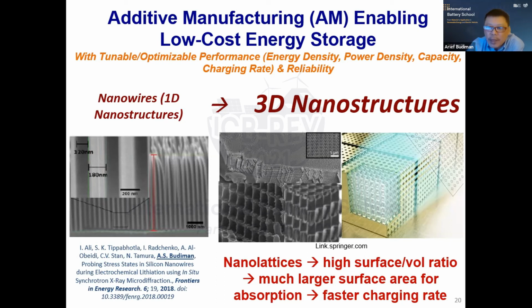Now that we realize that 1D is already so beneficial, at least in creating the compressive stress state, of course, there is some part that is in a tensile stress state, but with the model that we have, we can adjust it. We can try to design the geometry of the nanostructure, maybe 1D, 2D, 3D, so that the stress evolution, the damage evolution, can be minimized, so that we will have no cracks in silicon, which is the one big main issue of silicon. If we solve this, we will be able to have a fully 3D, fully 100% silicon anode.